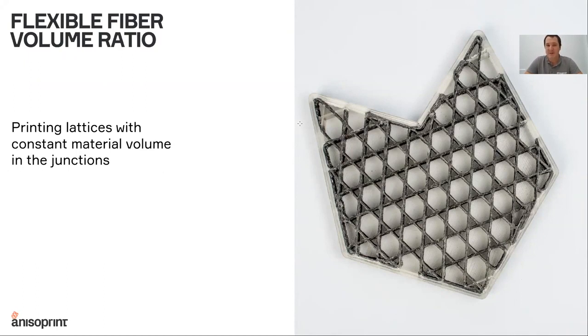So basically what happens at the junction point, the fiber volume is doubling, but we need to avoid doubling the material volume in this case. So in the intersection, we need to be able to locally reduce the matrix volume fraction several times, to not have an increase of thickness at the intersection point, and to be able to have the continuous fibers in the intersection.